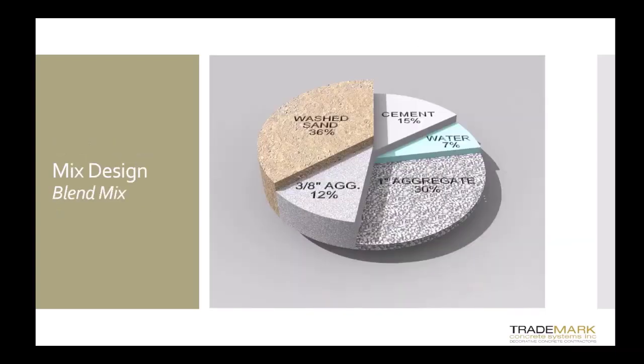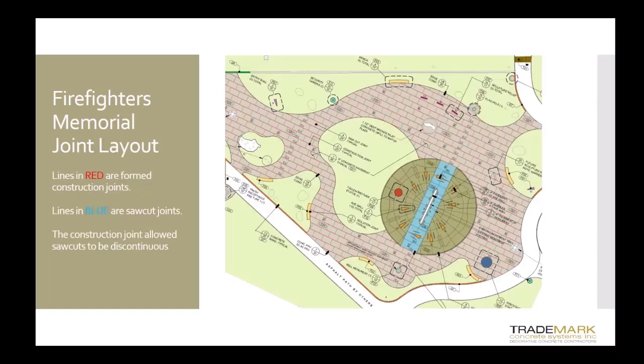We used a blended mix design, pumpable through a 3-inch line if needed. We were limited with some access issues at the grounds there. Probably the biggest hurdle as it came to concrete was the temperature. So 110 degrees in Sacramento in the middle of the summertime. So we just worked with Cemex, the ready mix provider, and we were able to get concrete at 5 a.m. every day just to make sure that we could control our pours.